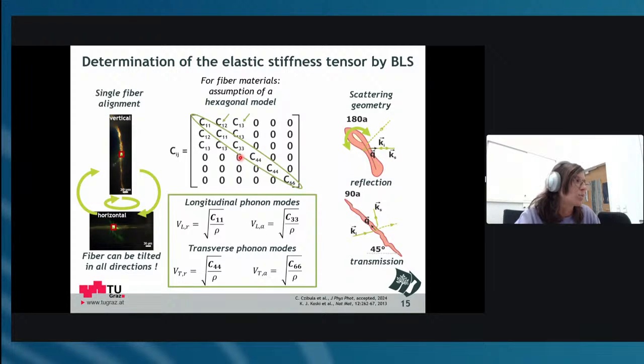And I would say the one in literature which you will find most is the 180A, especially in other life science applications. Now everybody will be writing about backscattering. And this is 180. You can see it as 180A or R, and this just depends on whether you tilt your sample a little bit or not. But basically what you do here is you shine the light into your fiber. This is Ki, and you collect in the same direction, that's Ks. And you will test your phonons. This is determined by Q in the radial direction of the fiber. So this is a reflective geometry.